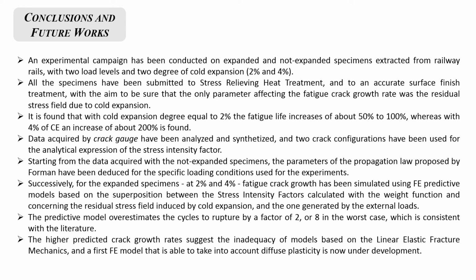2% of cold expansion gives an increase of the fatigue life of about 50% to 100%, whereas with 4% of cold expansion, an increase of about 200% is found. Data acquired by crack gauge have been analyzed and synthesized, and starting from those concerning the not expanded specimen, the parameters of the propagation law proposed by Foreman have been evaluated.